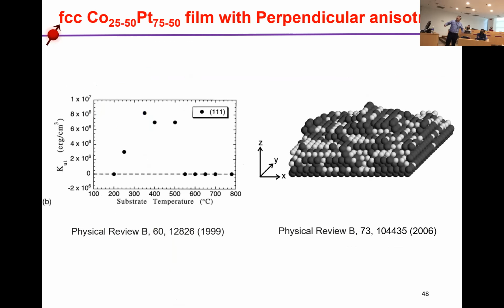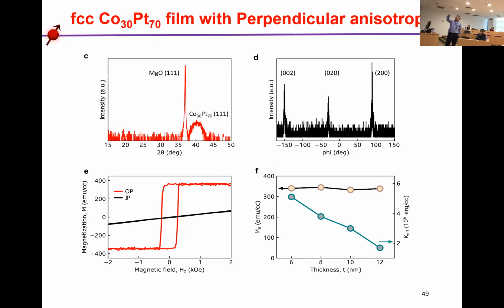And now we use the composition gradient and the threefold symmetry. We designed another material, FCC cobalt-Pt, which has perpendicular anisotropy, but close to the interface they form layered structures. The clusters form layered structures. So based on this, we deposited FCC cobalt-Pt materials. From here we can see the threefold symmetry, and with increased thickness, the magnetic structure decreases because the layered platelet structure is close to the interface.